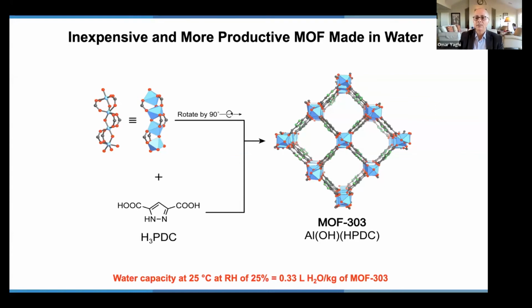And the nice thing about reticular chemistry is that you can go from potentially a material that is expensive like zirconium into a material that would be a lot cheaper with aluminum. So aluminum is cheap, and you can use it to make this MOF. This is an amazing MOF we call MOF-303. It's made from aluminum rod oxide SBUs and this linker, which you can buy.